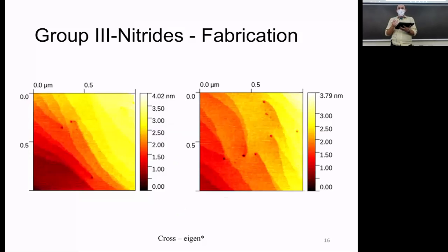And this is what we're getting. You can see nice crystal structures here. You can see these layers, followed by another one. I'll get the laser pointer working. Another layer, another layer, another layer. And each of these is a single layer of material stacked on top of each other. From this picture right here, we can actually determine part of the lattice structure of this material. You can determine how thick each layer is, and so you can know what the constants of your lattice are.